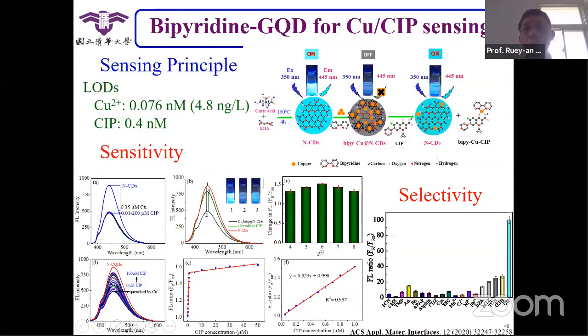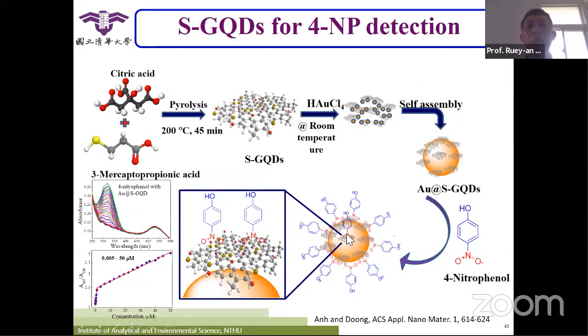Oh, okay, I forgot to mention, we just published this paper last month. You can also use this to detect some environmental pollutants like nitrophenol. We use citric acid and some sulfur salt, mercaptopropionic acid, and then we put the gold precursor inside. Since the GQD is a reducing agent, it can reduce the gold ions into gold nanoparticles, so that we get the gold GQD, and then we can use this to decompose nitrophenol as well as to detect it. Their efficiency is also quite good.